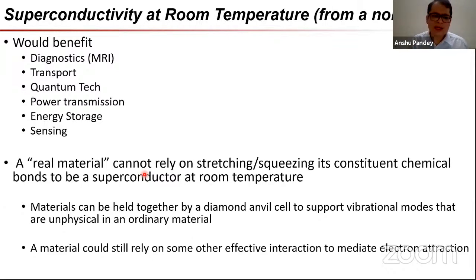There are a few caveats to that. A material could either be not held together by its own chemical bonds, but rather held together by a diamond anvil cell, which means under extreme pressure. And then in that case, it can support vibrational modes which are formally unphysical in an ordinary material. And such materials have been shown to give rise to superconductivity. But again, there's a trade-off there, because you're trading off having to go to low temperature with having to be at high pressures. There's a big trade-off there. Not sure if that's a win-win at all.